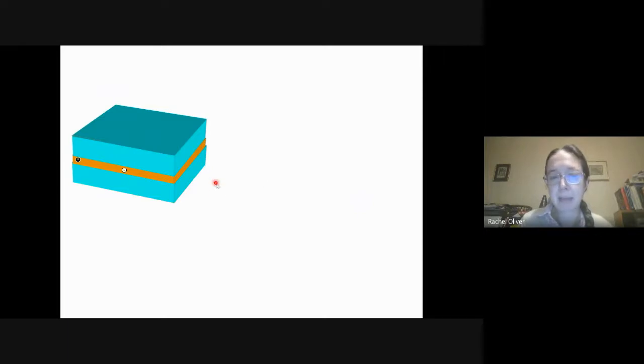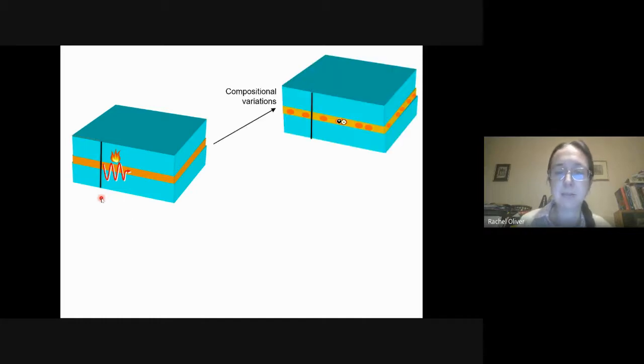And what we would expect to happen in a quantum well device is that if a dislocation is present, the electron and hole, although they are trapped by those energy differences in the direction across the quantum well, are able to move around within the plane of the quantum well. And that would mean that they could move within the plane of the quantum well and often find the defects and recombine. And if there are lots of defects, lots of dislocations, that becomes more likely. We get lots of heat out and the device doesn't work. That's essentially what we understand as the problem in gallium arsenide devices when they have a high density of defects.